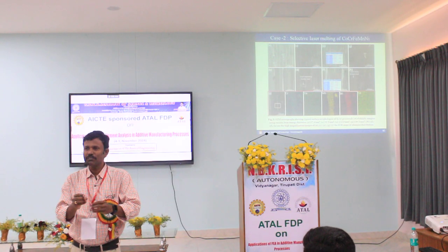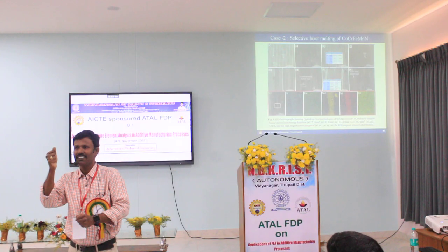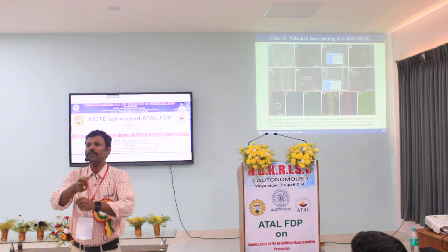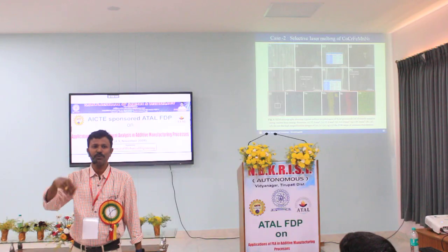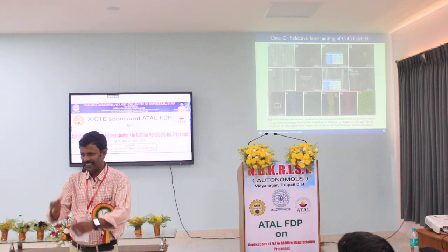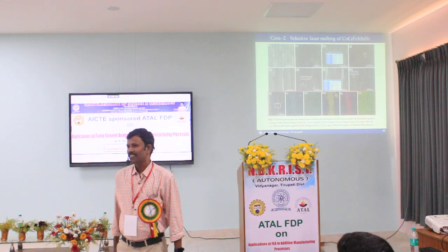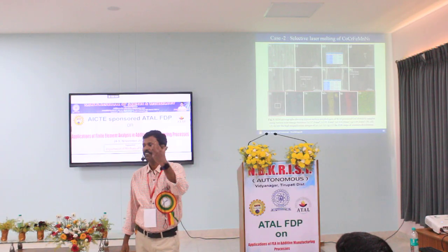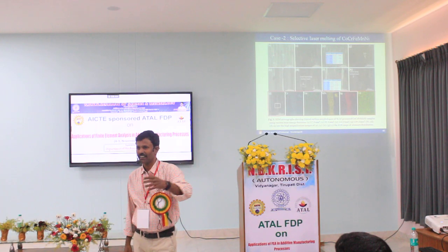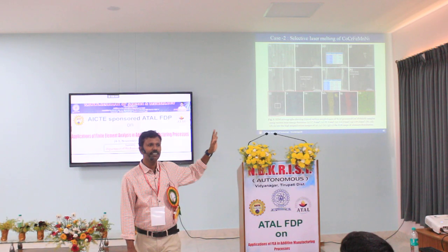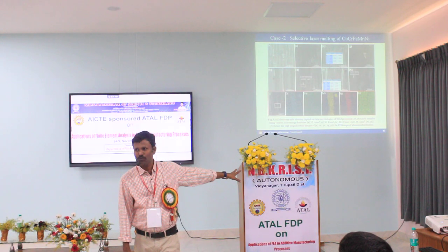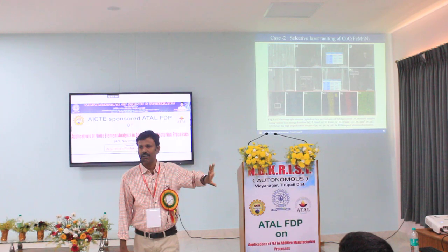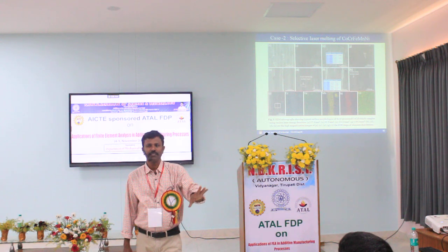We realized that we had taken one sample and tested it, which is supposed to give 2000 megapascal, but it gave only 10 megapascal. Our doubt was correct. When we did fractographic analysis and other things, it clearly demonstrated that this phase, evolved as a result of selective laser melting, is the culprit.